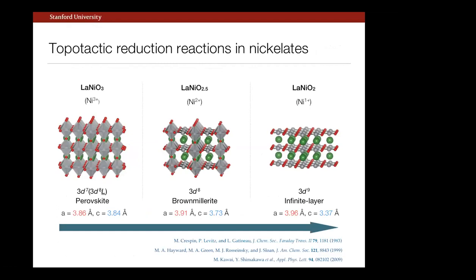As you may know, the most common oxidation state for nickel is nickel 2+, so nickel oxide, this famous Mott insulating compound. A secondary valence is nickel 3+. Starting in the early 80s, very clever chemistry efforts discovered that you could do something they termed a topotactic reduction reaction. They started with lanthanum nickel O3, a perovskite version of this compound, and then they could deintercalate rows of oxygen to make the so-called Brownmillerite structure. So here's the formal chemical formula. If you go even further, this, by the way, would correspond to nickel 2+. And if we take the other row out, you get indeed this direct analog to the infinite layer cuprates and a formal valence of nickel 1+.